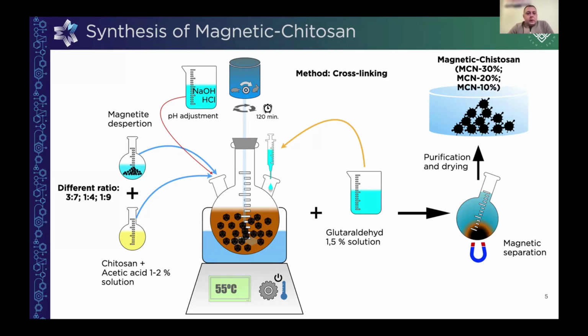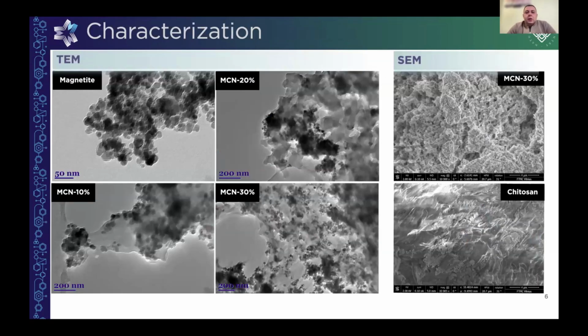So after that, we dispersed magnetite in water and added it to the chitosan dissolved in acetic acid. And after the synthesis, by using the cross-linking agent glutaraldehyde, we got the magnetic chitosan sorbent that was simply separated from the synthesis solution by a magnet and then purified, dried, and used in our experiments. So for characterization, we used the TEM and SEM methodologies.